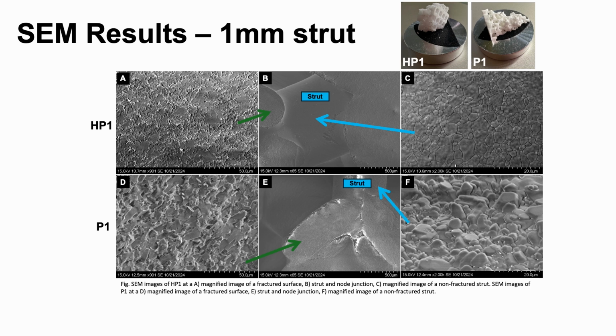When we did a close-up of the unfractured strut in C and F, we see that the particles in C are more closely packed together than the P particles in image F. As shown before, we know that there was a liquid phase sintering that was induced by magnesium, calcium, and silicon at high temperatures. Since there was a rearrangement of particles, it may have been a result of small pores seen in F, and therefore leading to pore packing and ultimately lower strength and modulus.